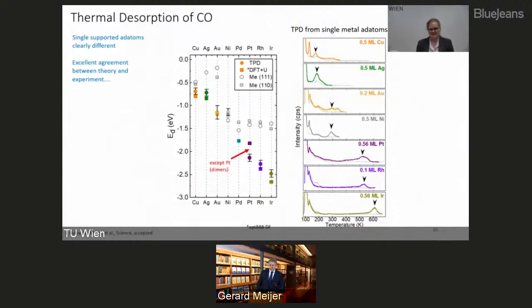Does it happen for others? The answer is no. So actually for palladium, there is no experimental data point there because palladium is even worse. If you put CO on palladium, it starts to not make dimers, but immediately make much, much bigger clusters. For rhodium, it doesn't happen. For rhodium, we can put CO, and it doesn't make this aggregation. So I don't think it's generally true. You have to read it in each individual case and see, and we can with STM see if they aggregate together or not.